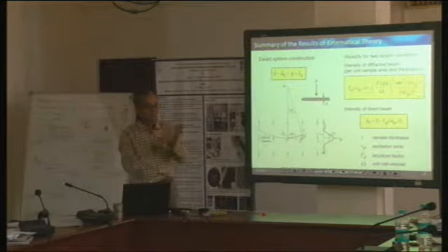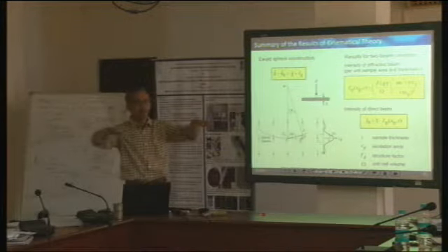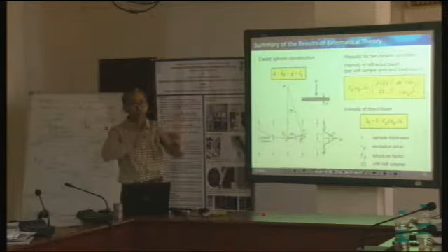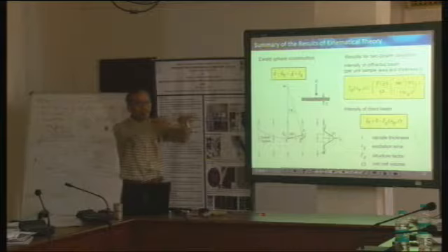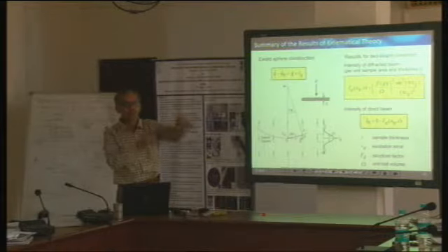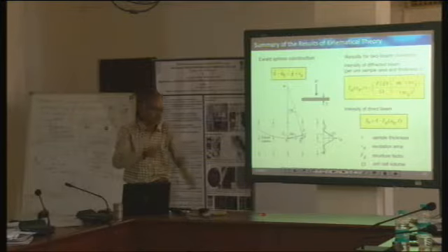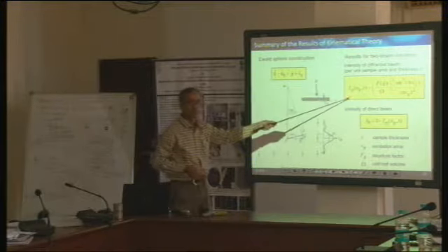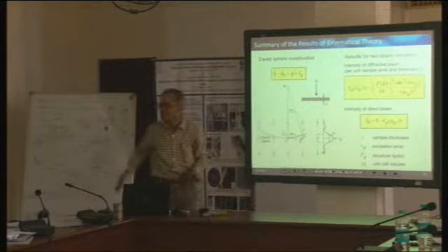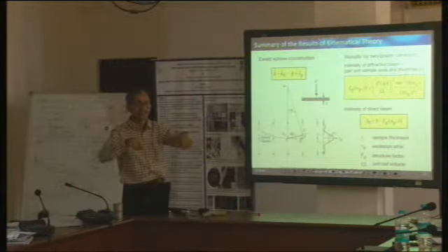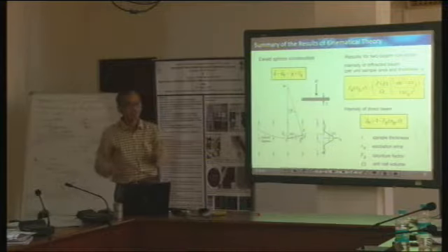Suppose I have a plane sample and somehow I thinned it, and because I thinned it, it got bent. So locally it is bent everywhere, somewhere more, somewhere less, etc. I put this sample under the electron beam, and this is the equation which is going to play out in getting the diffracted beam intensity. So depending upon the S parameter, I will get different intensities everywhere.